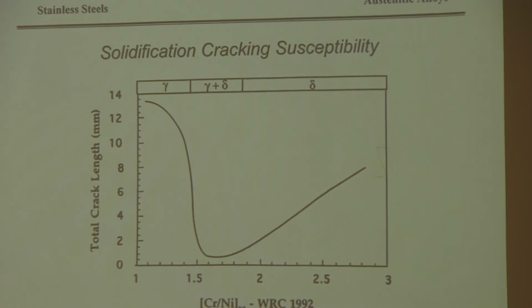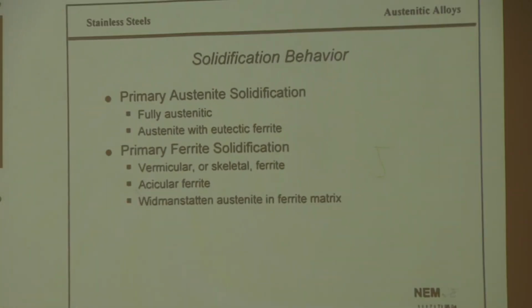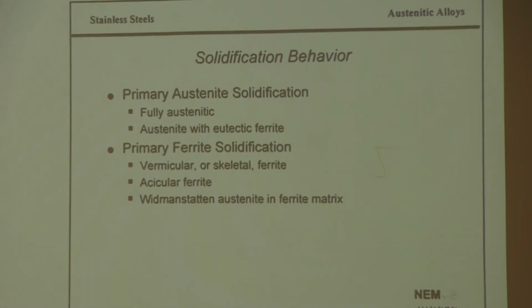And so in order to avoid cracking in your stainless steel welds, you really want to solidify right in this region right here, which is austenite with just a little bit of ferrite. And solidification behavior of stainless steels is actually something that you could teach an entire course on. So I'm going to try to go through it quickly enough, but in enough detail that I can give you some understanding.